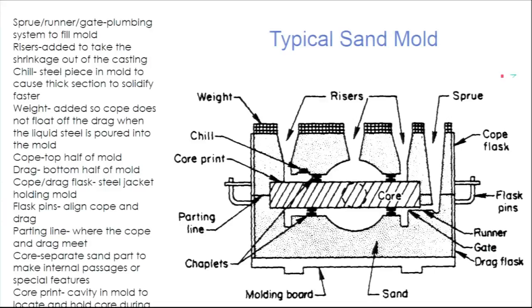A core makes holes inside the casting. Castings are really clever because I can make any shaped hole I want to on the inside. One of the problems with manufacturing processes is there are no good ways to make inside shapes. So we may have to make two pieces and put them together to make an inside shape. In steel castings, we can't violate that rule, but we have a really clever solution. We make a sand piece with the glued sand that the outside shape is the inside shape you want, and then we pour steel around it and let it burn away.